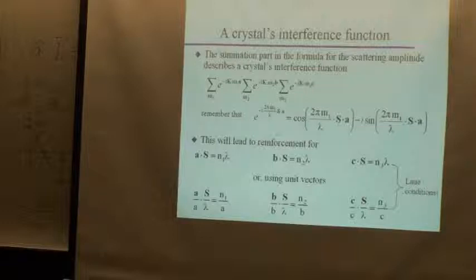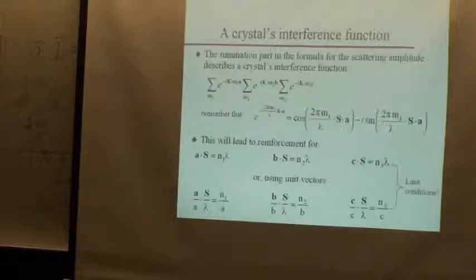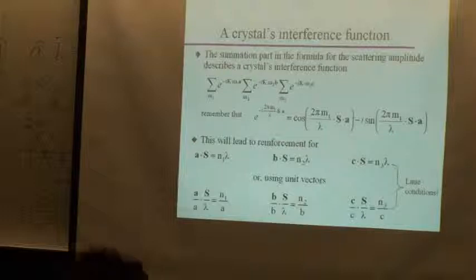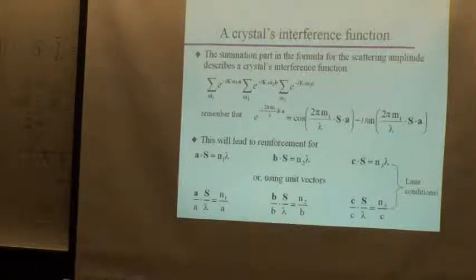Okay? Now, why is that important? Well, if you look at this, you multiply by these three sums. If one of them is 0, what does the entire expression become? 0. Okay? So, the only time that this sum will not be 0 is when this is fulfilled. Because then all the cosine expressions will be 1. None of them will be negative, and so on.